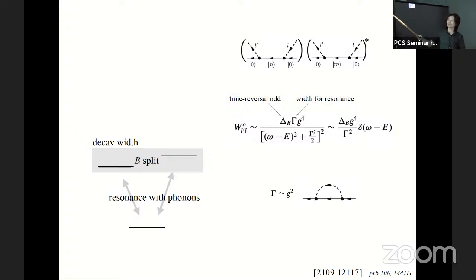And then you find that there is a G to the fourth over gamma squared. But the width gamma also comes from the intermediate state emitting and reabsorbing a phonon. So it's proportional to G squared at leading order. So overall, the resonance skew scattering is independent of the coupling constant between the phonon and the defect. So even if the coupling is small, because of the resonance, the effect can be large.